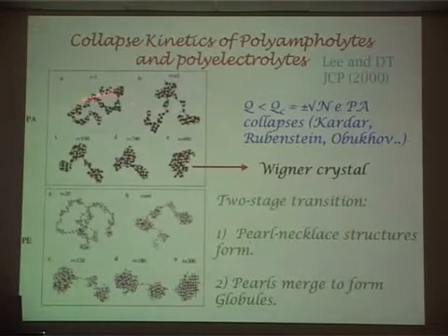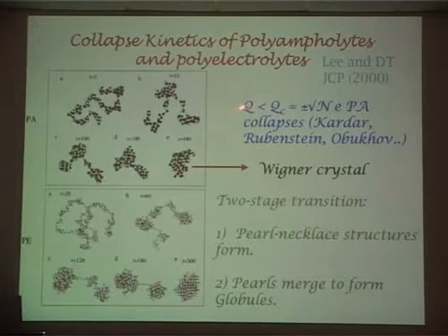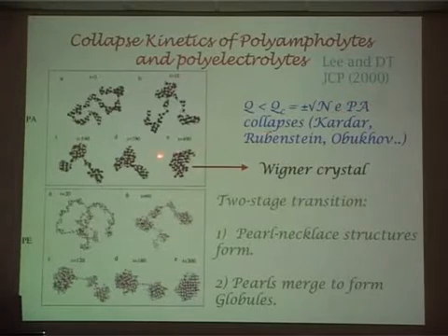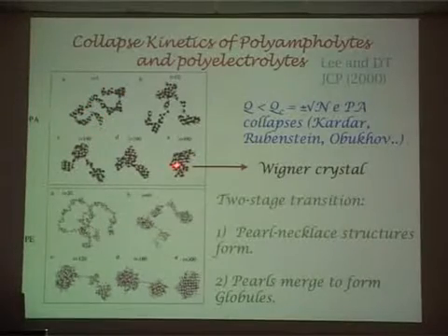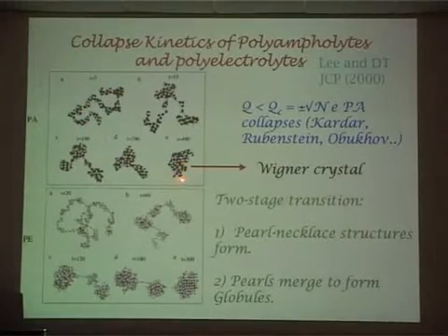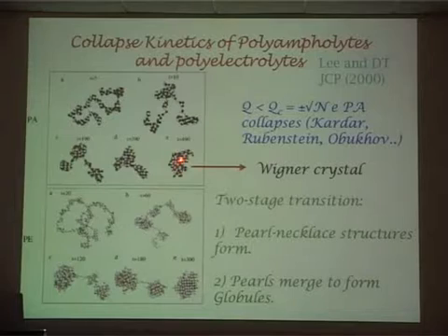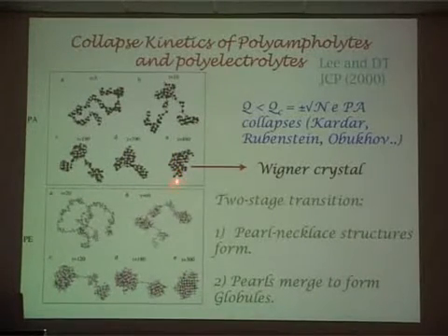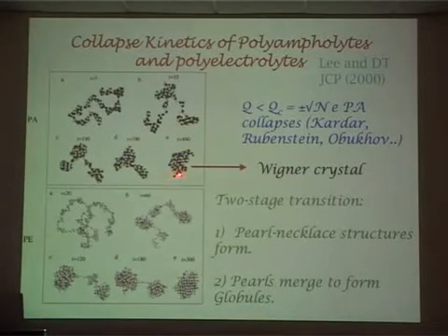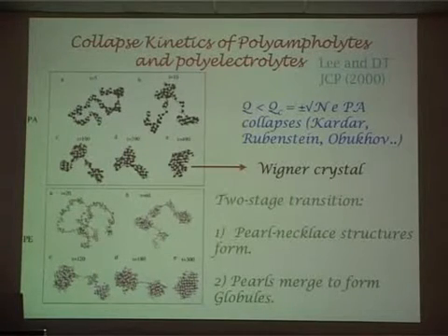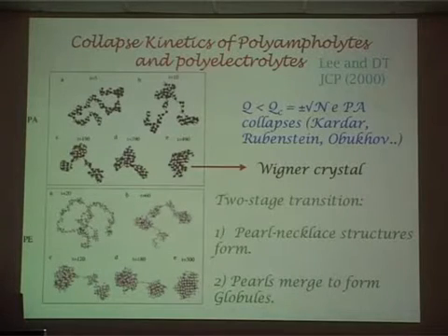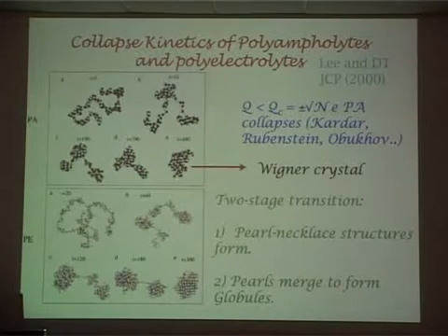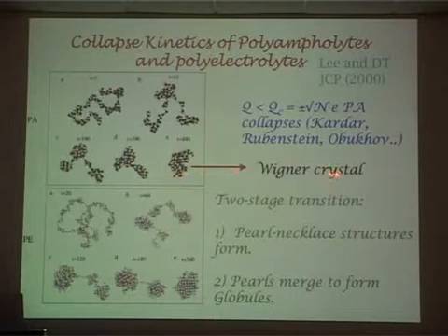This is a computer simulation of a polyampholyte with charge less than QC, which is square root of n times E, and it starts from an unfolded conformation and goes to this compact globule. You can look at the pair functions of this compact globule, and they are in fact arranged in a perfect BCC lattice in which the lattice sites alternate between counter ions and the charged monomers. So it's really a piece of a small Wigner crystal.